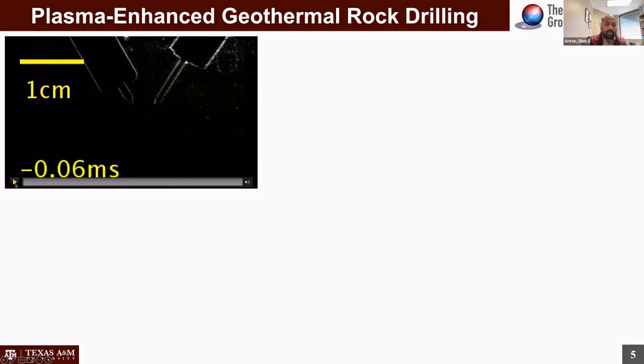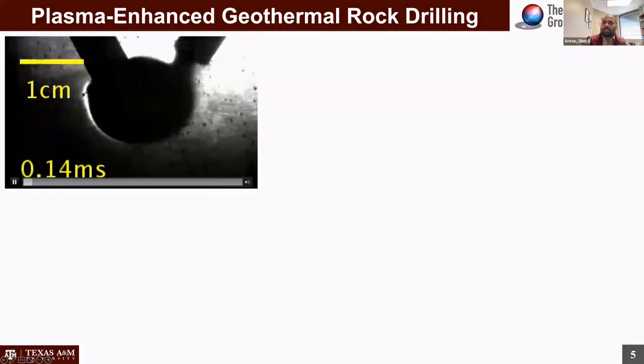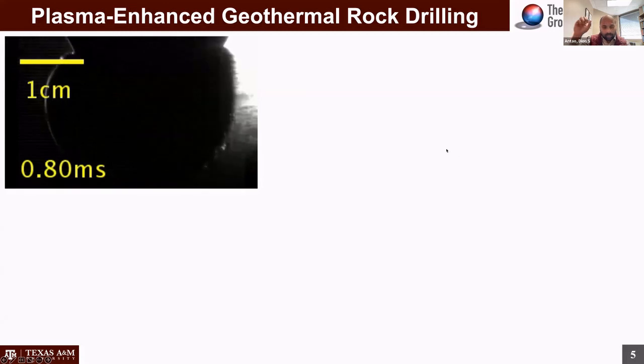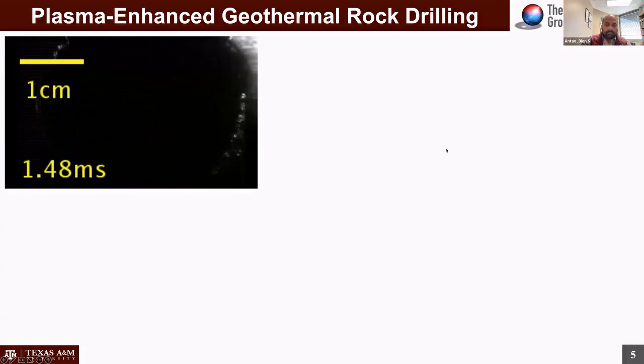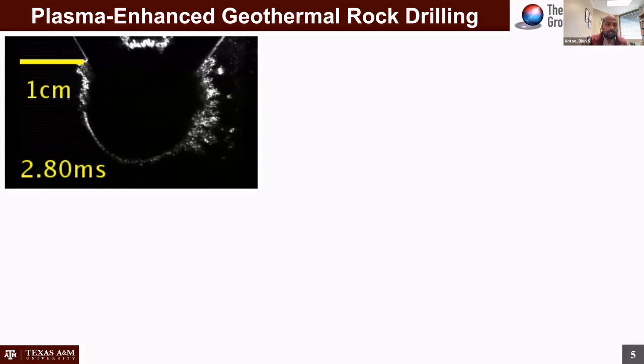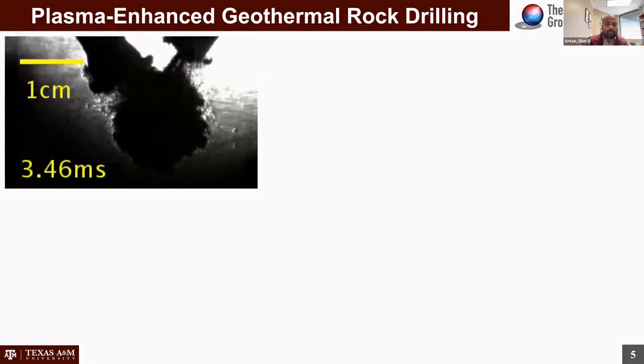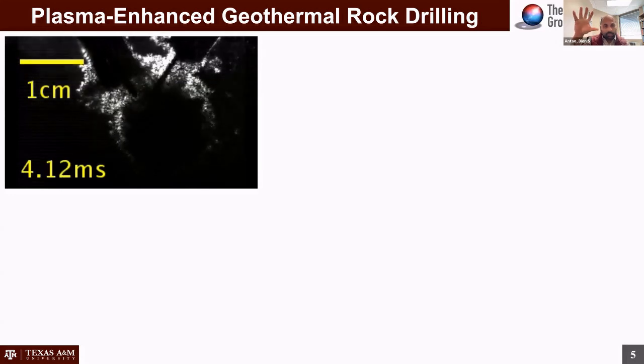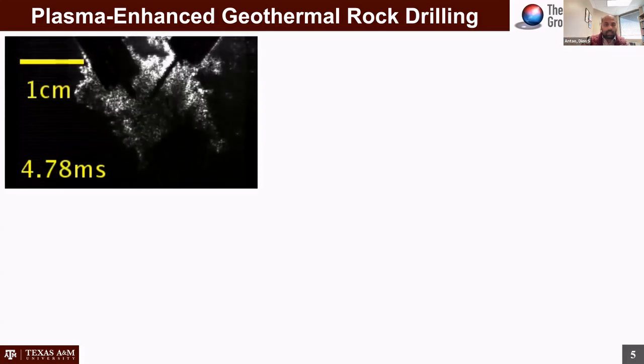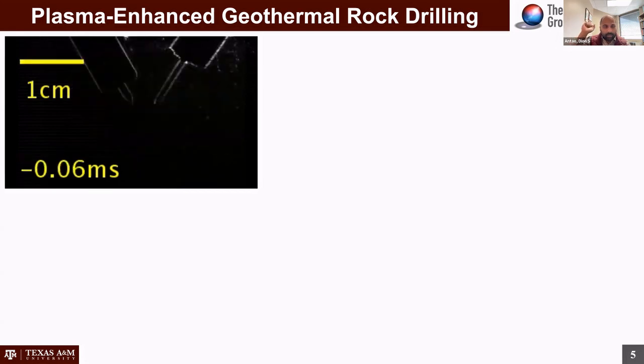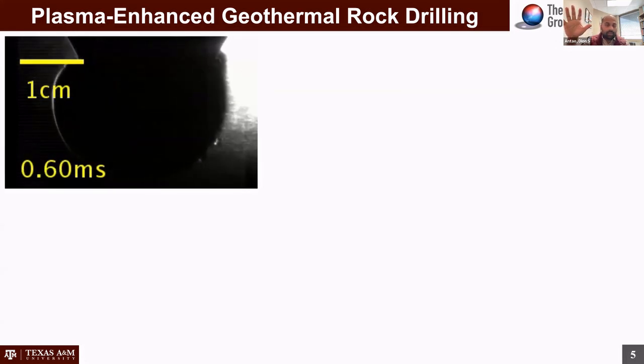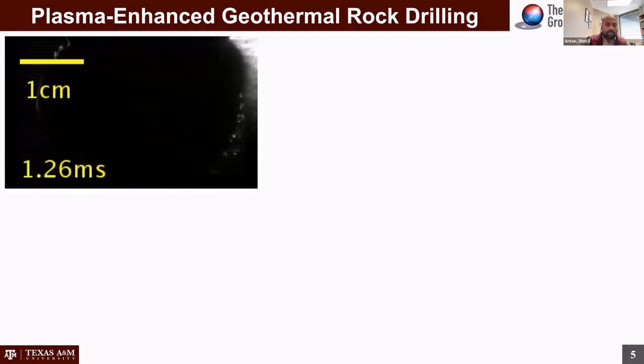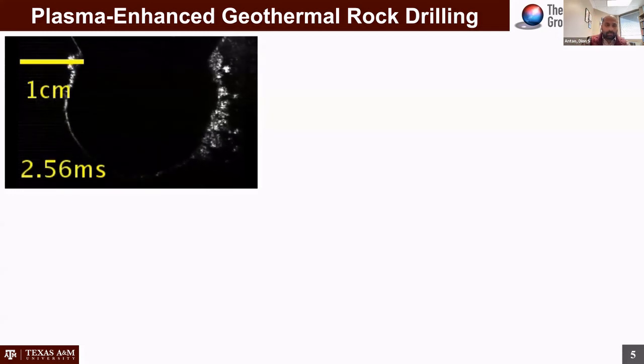Lightning's accompanied by thunder. And so what you will see is this formation of the plasma, and accompanied with that initial plasma singularity, there is a bunch of shock waves that go out. The shock waves have extremely high pressures. You form this bubble, and the bubble collapses. You have this cavitation singularity, and each time you have that singularity, another shock wave is generated with high pressure, and that bubble constantly oscillates, but I'm just showing you the first cycle.